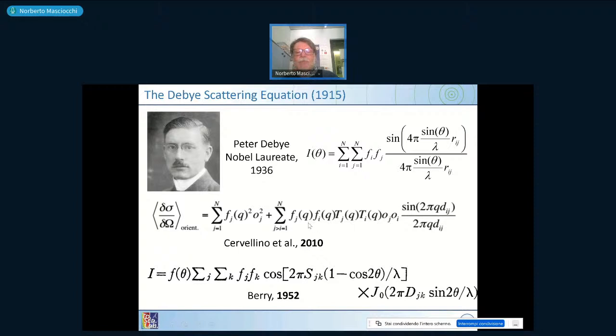and this sequence has again the atomic scattering factor of each atom, a temperature factor, which is how every atom moves, and its occupancy. And here you have again q. This is small q, nothing else than 2 pi sine theta by lambda, and the distance between the two atoms.